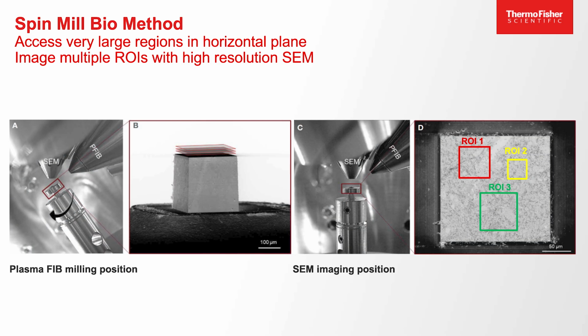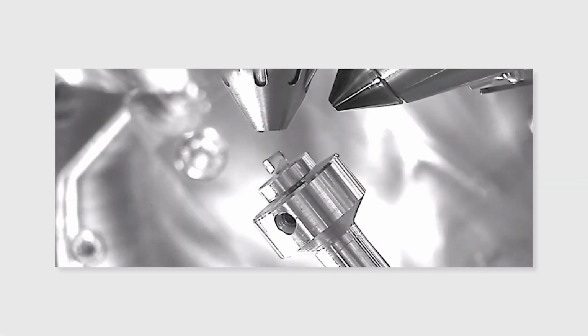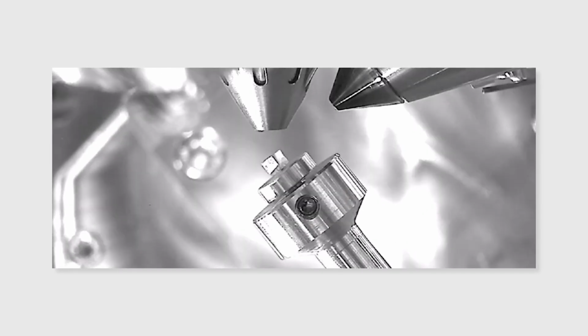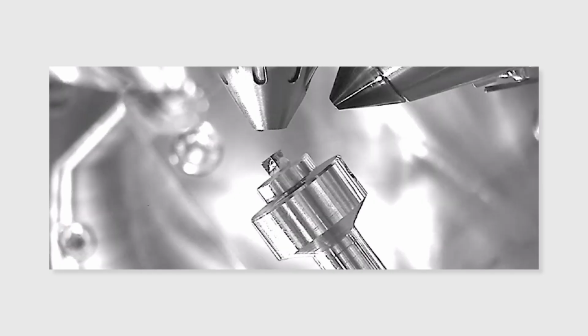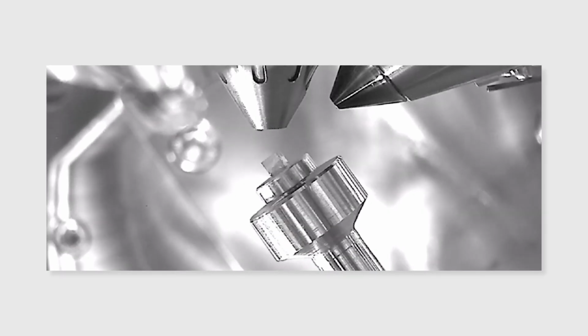Of course. We touched a little bit on the power of plasma to access large volumes, and this is obvious for the classical cross-sectioning approach, but Hydra Bio is also offering a novel application, which we'll call spin mill. The power of this is that now you can access the sample in its horizontal plane by milling at glancing angles. This allows you to open a very large area of almost 1 millimeter in diameter, and then subsequently image the areas of interest. We call this spin milling because while the sample is milled, it's also being rotated at predefined positions, and therefore the name spin milling.